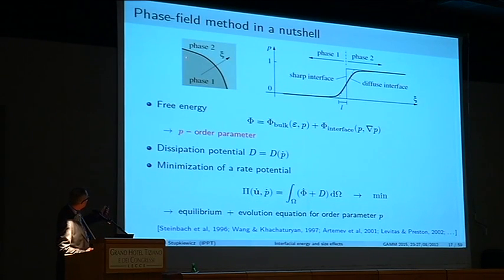Anyway, if we consider an interface between two phases and we think of an axis Xi passing from one phase to the other, we can introduce a parameter P which varies between 0 and 1. You could think of a sharp interface when you have a jump in this P, but you can also introduce a smooth diffuse interface concept when this P varies smoothly with some characteristic length L, which will describe the thickness of the interface.